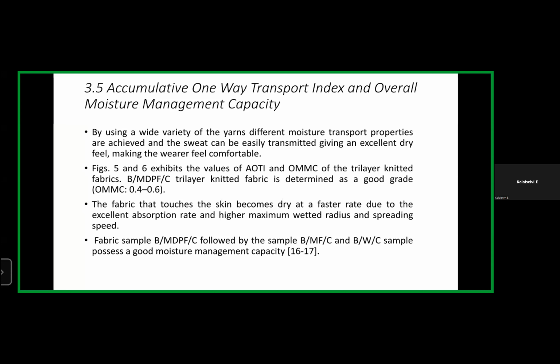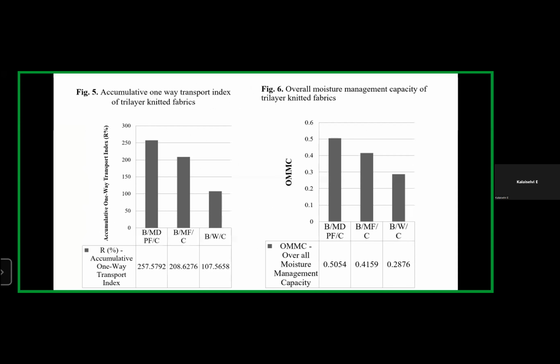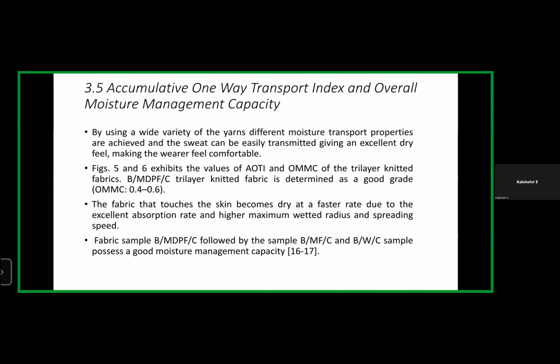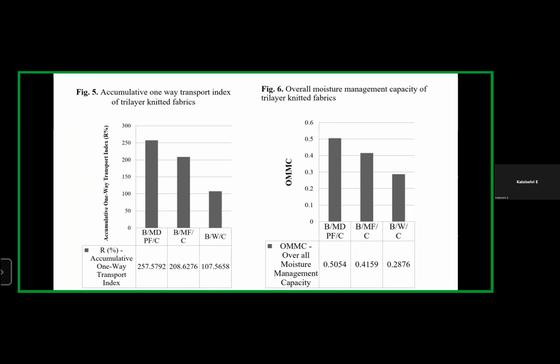The fabric that touches the skin becomes dry at a faster rate due to the excellent absorption rate and higher maximum wetting radius and spreading speed. So through the results, you could see the bamboo microdenier polyester filament stands first in the result, followed by the other 2 samples.